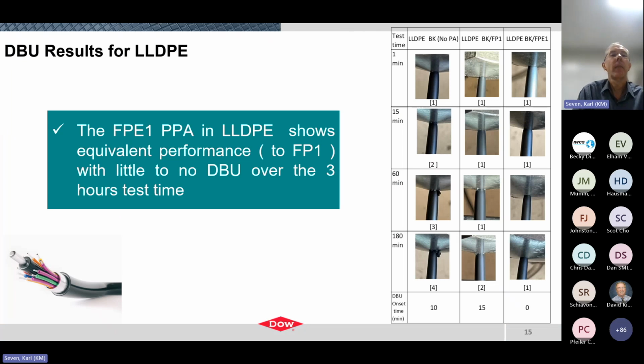So here, given the good performance we saw with the polar polymer additive, as I mentioned, we extended out and investigated this same additive in a linear low density jacket system, and I'm capturing those results here. The series of pictures on the left is a comparative sample with no processing aids, so a fully formulated jacket, and we typically see a very high amount of buildup throughout by the end of the time period.